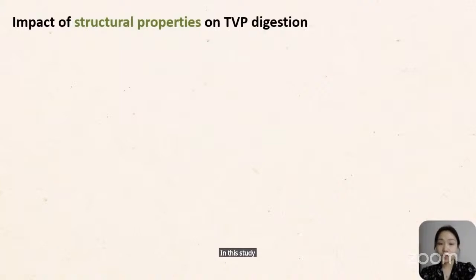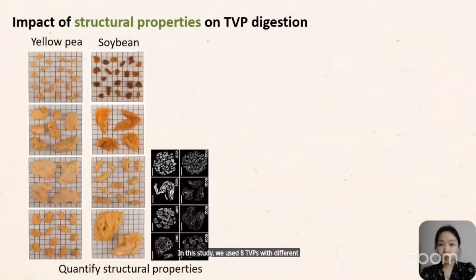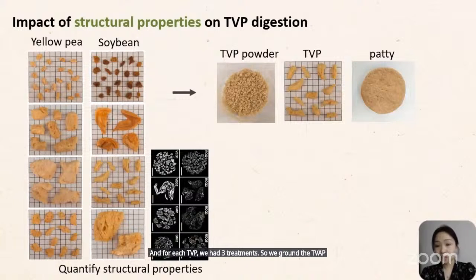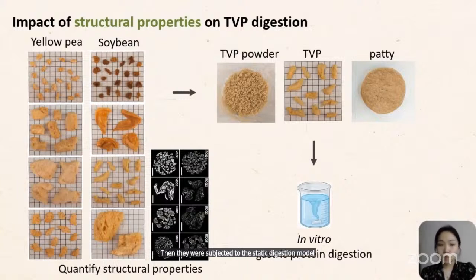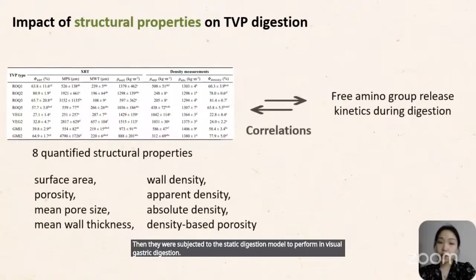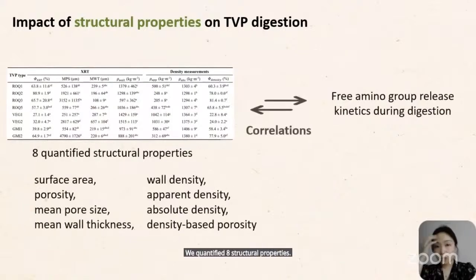In this study, we used 8 TVPs with different structural properties, and for each TVP, we had 3 treatments. So we ground the TVP into powders to remove the porous structure as a control group. And we had the original TVPs, and we also made plant-based patties from these TVPs. Then they were subjected to the static digestion model to perform in vitro gastric digestion. We quantified 8 structural properties of TVPs, then we correlated them with the free amino group release during digestion. We got many results, but for the sake of time, I will just show part of them.